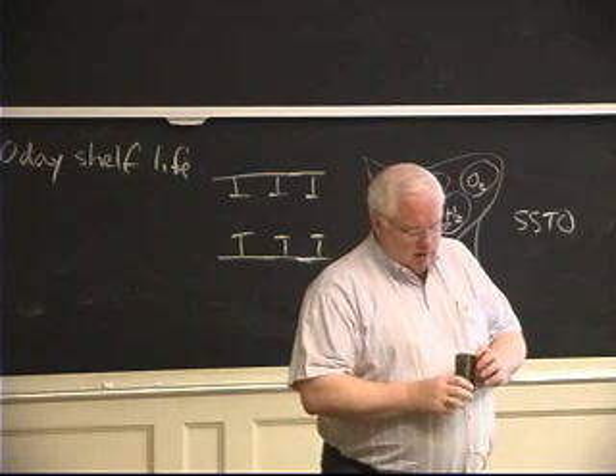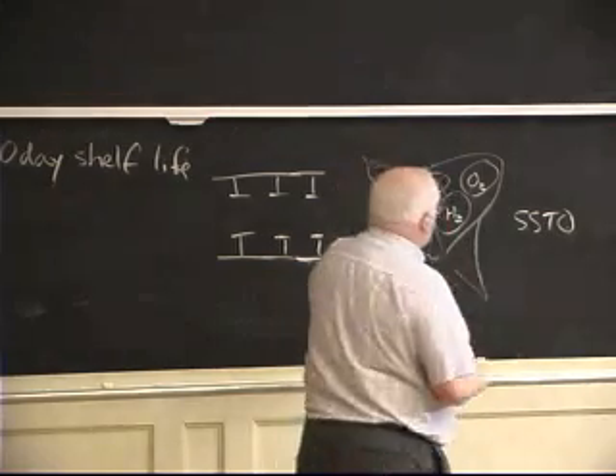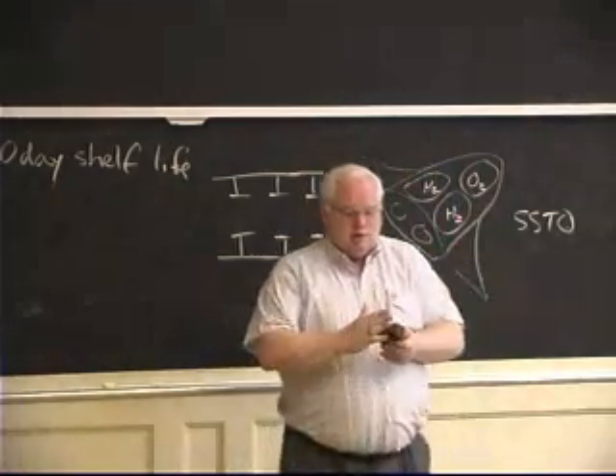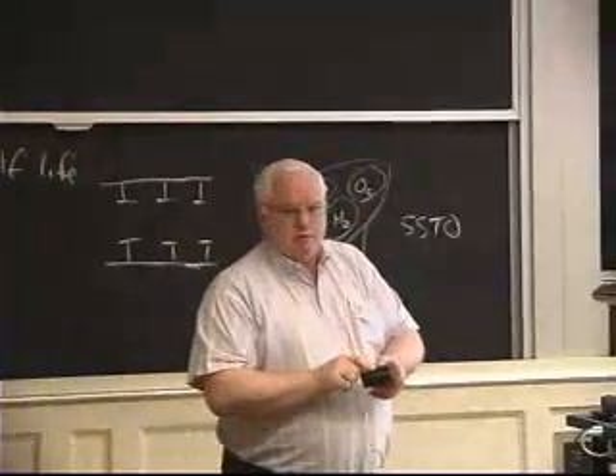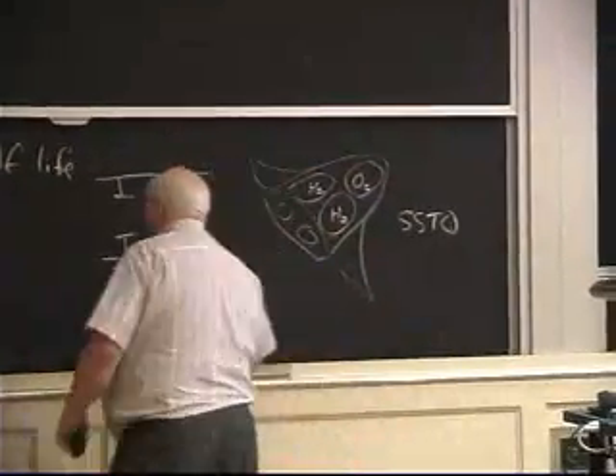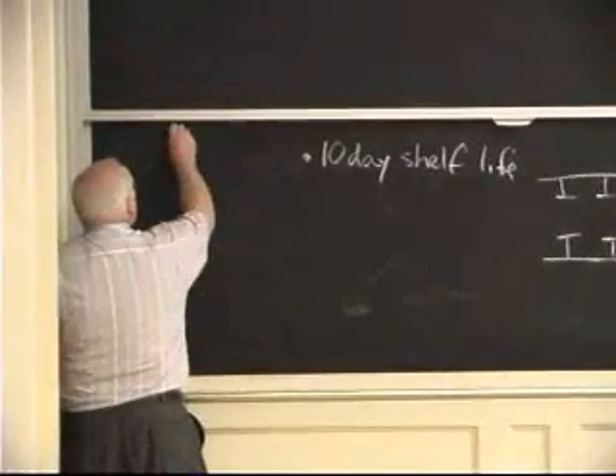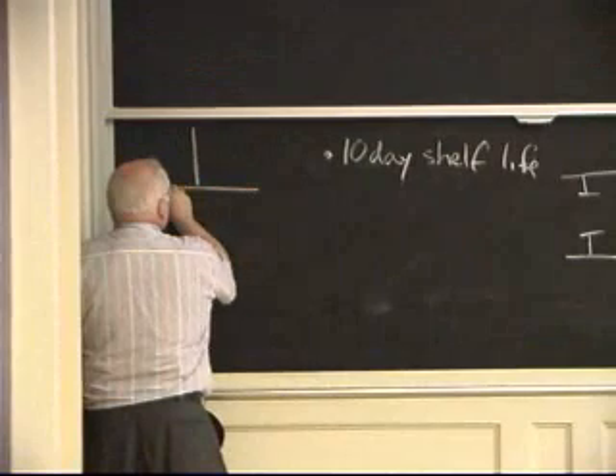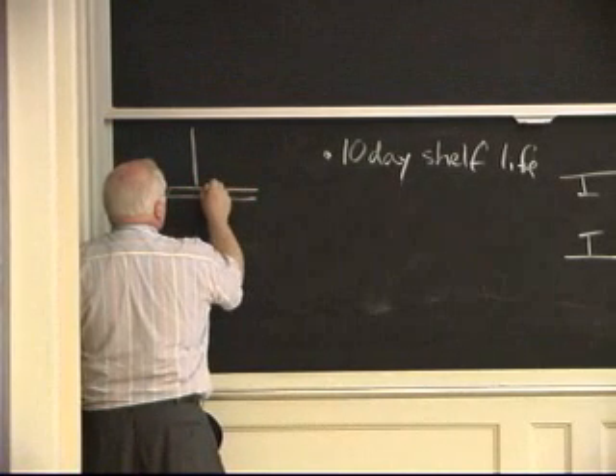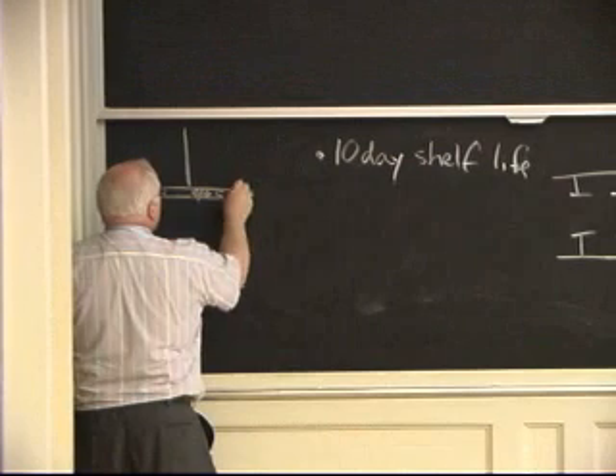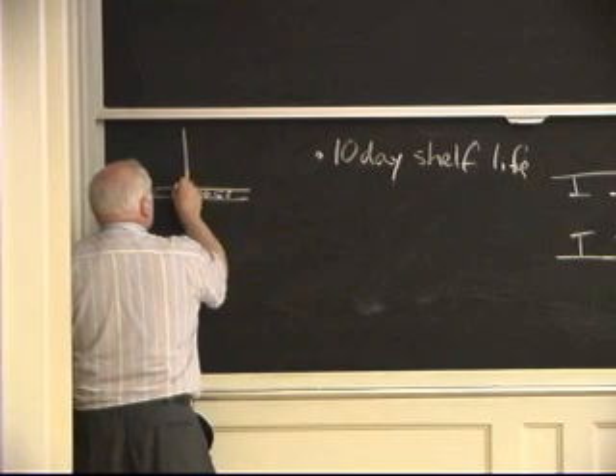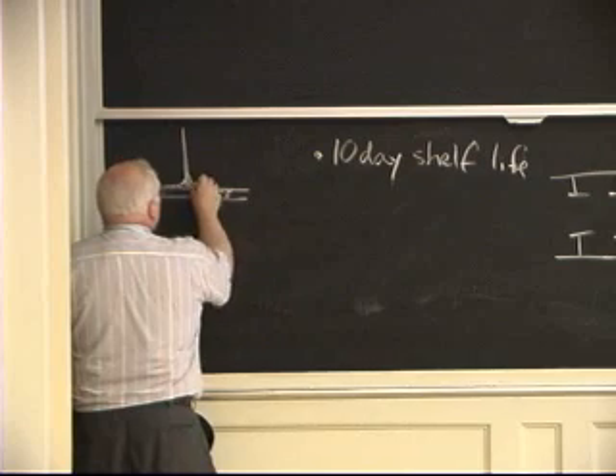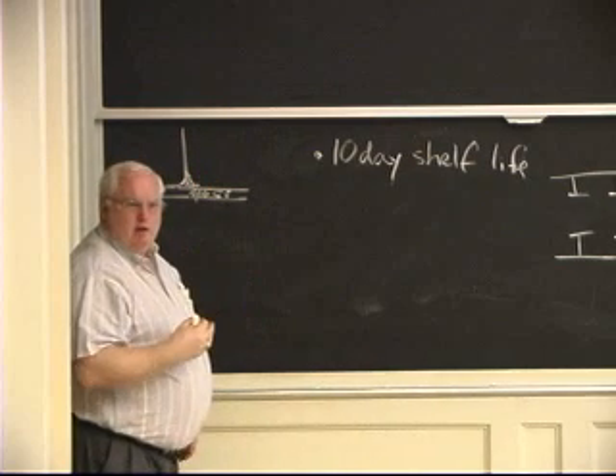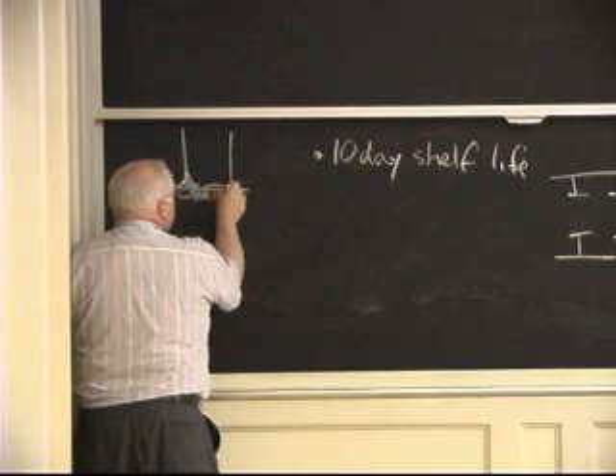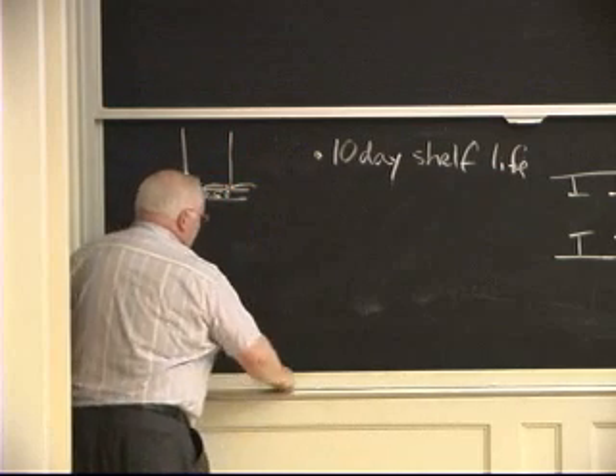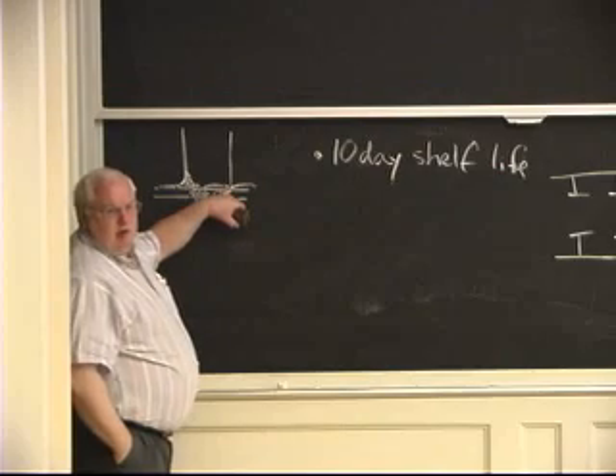So it turns out they did all this, and 2 of these 10 things came out with blisters on the skin. The surface delaminated from the Hexcel foam, and if they looked at it carefully, they would see this is the Hexcel foam and this is the carbon composite, or the graphite epoxy composite. What they wanted was a nice adhesive bond where they got flow of the adhesive and a nice wetting contact angle. You want to get wetting of your adhesive. What they actually got, if I pass this around, you'll see they had the adhesive with no real contact there, lousy contact. It didn't really wet.